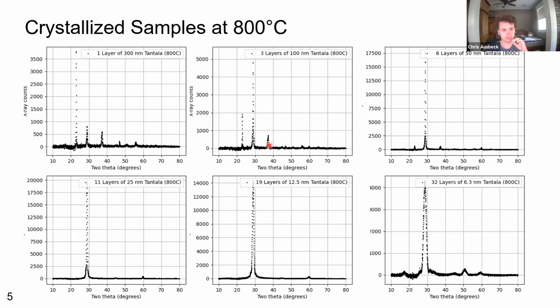We also see the 36-degree peak as well. In 6 layers of 50 nanometer tantalum, we see that the 36 and 23-degree peak have diminished further, and the 29-degree peak has gotten even bigger. This trend continues in 11 layers of 25 nanometer tantalum, where the 29-degree peak is even bigger, and we can't see the 23 or 36-degree peak anymore. And the same thing happens in 12.5 nanometers as well as 6.3 nanometers.